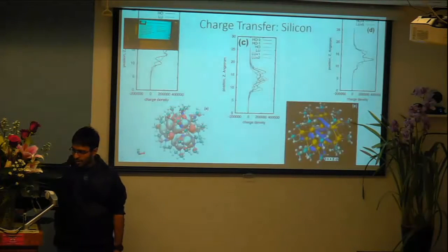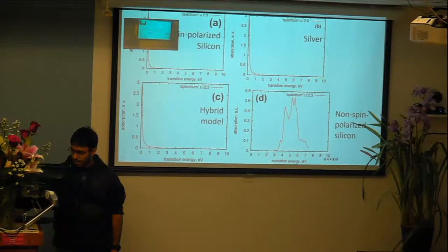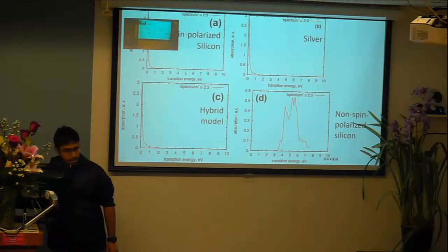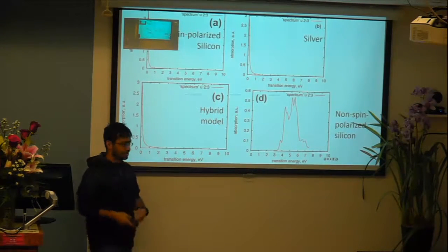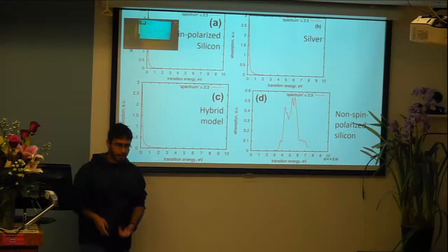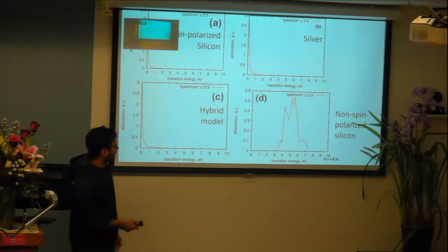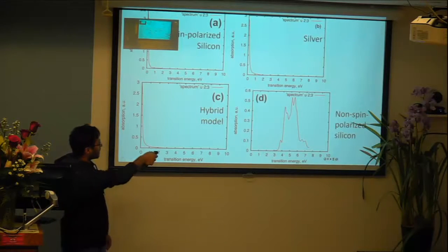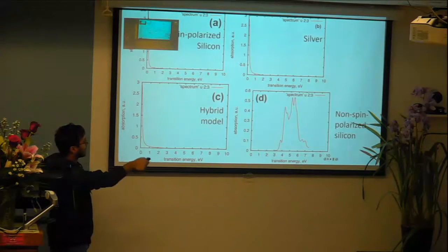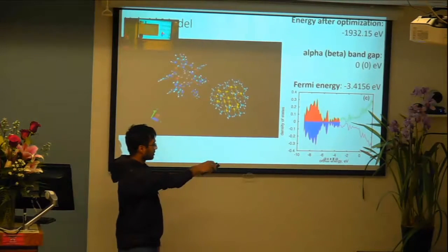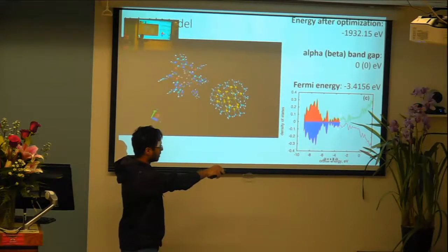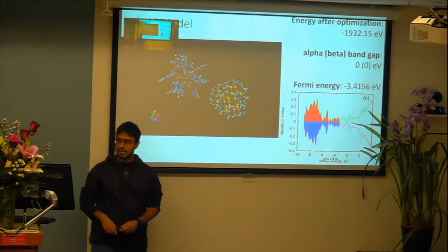Yeah, so I'll go back to the plots, right here. The question was what the significance is of this absorption spectra having a peak at 0, how it could be removed, and if it's real or not. So the peaks near 0, right here in the spectra, were actually a consequence of having the HOMO and LUMO states be very close to each other.